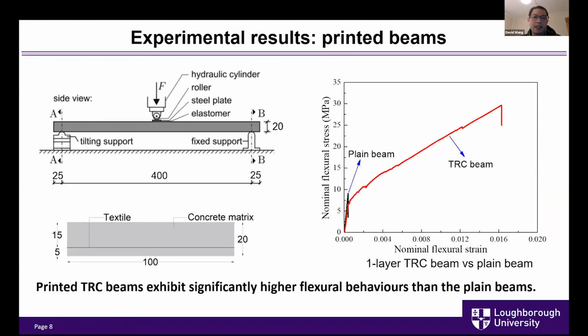Here are some experimental results. This figure is the comparison between the printed concrete beam and the 1 layer textile reinforced concrete beam. As we can see from this figure, by using only 1 layer of textile, both the strength and the ductility of the printed TRC beam is significantly higher than the unreinforced printed concrete.